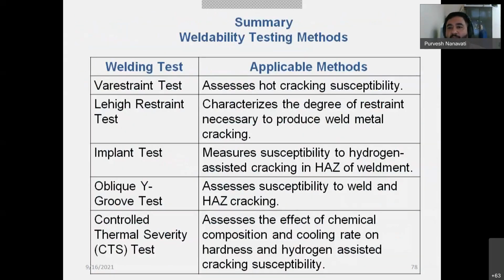So, as a summary, these are the various weldability test methods: Varestraint tests for hot cracking susceptibility, the Lehigh restraint test for weld cracking, the implant test for hydrogen assisted cracking, the oblique Y groove test for HAZ cold cracking, and the controlled thermal severity test to assess the effect of chemical composition and cooling rates on hardness.